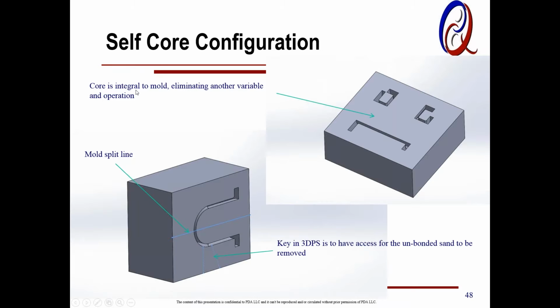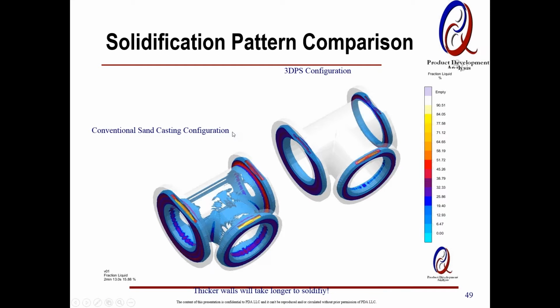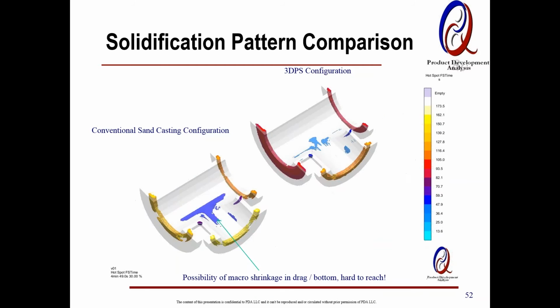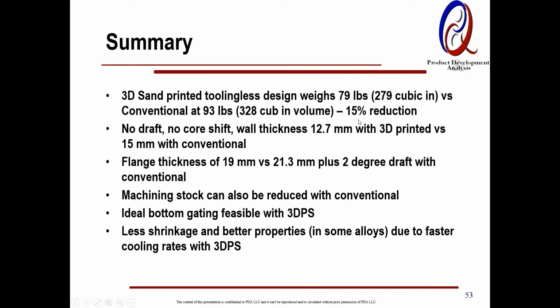We also thought there is a possibility of making a self core, so you really don't have to have a core even with the 3D printed. And there are ways you can get the loose sand out by creating the pockets, unbonded sand. And we gained 15% weight reduction here.